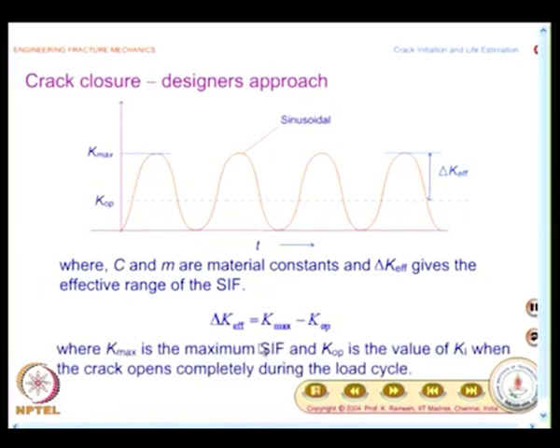So, delta K effective is K max minus K_op, where K_op is the value of K1 when the crack opens completely during the cycle, and this is difficult to evaluate, but we have to do that if I have to embed crack closure in our crack growth calculation.